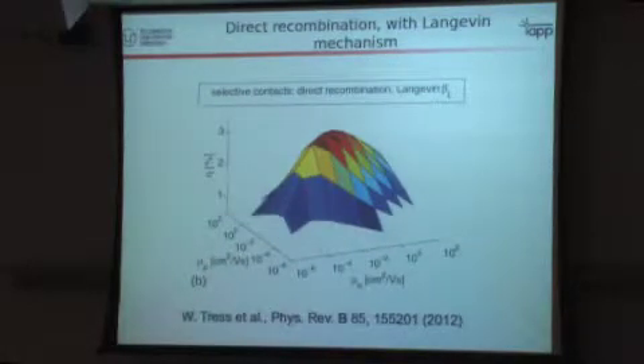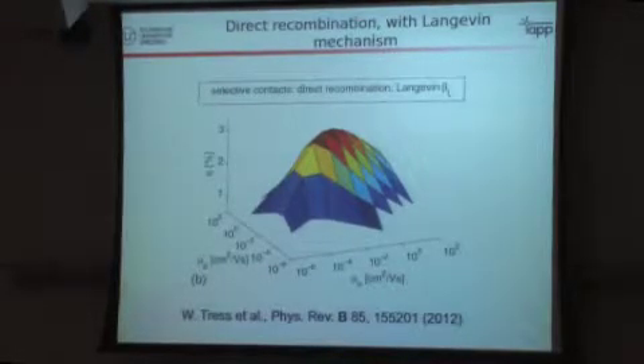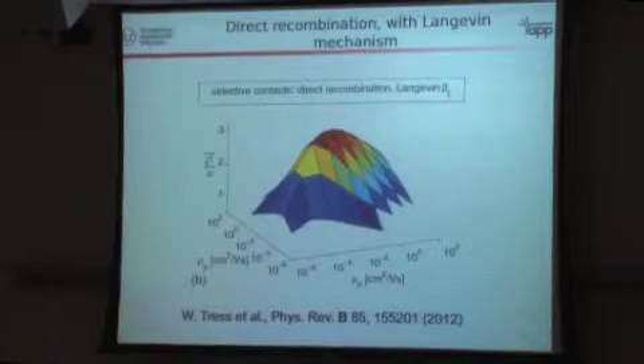Now, if he takes the more appropriate Langevin theory, things look more complicated. You again increase the efficiency with mobility, but 10 to the minus 3 is now a maximum. And when you go higher in mobility, efficiency goes down. If you look at the details, it turns out that very simply, the higher mobile the carriers are, the more recombination you have. Unfortunately, we couldn't yet experimentally test this because we cannot reach this regime. We have moved up here, that seems to be true, but we haven't had these high mobility materials to move down.